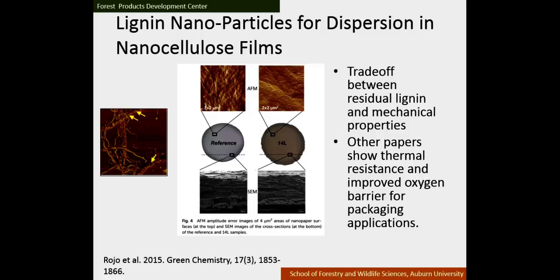Another thing she found was those little nanoparticles, when you process it, you get a smoother surface on the right side from when you have the nanolignin on there versus if you don't. And that's where the lignin easily flows under a temperature, and so it can flow and redistribute itself and then attach the composite back. So this has applications towards packaging and other similar applications. That's sort of what she's working on.